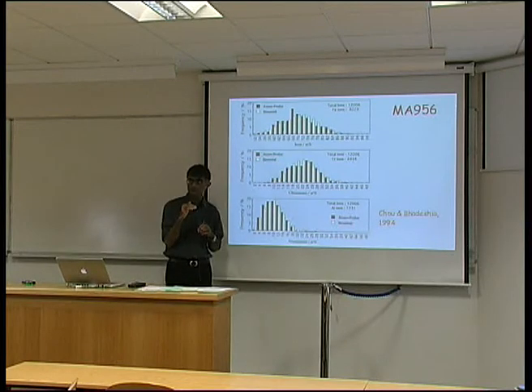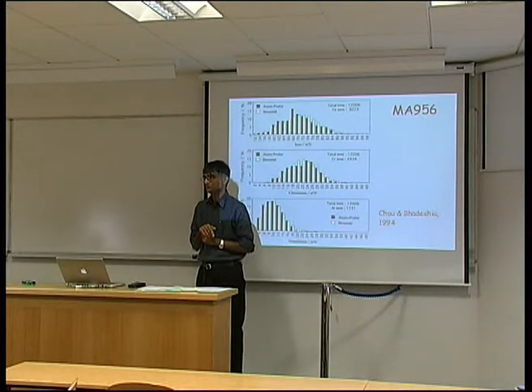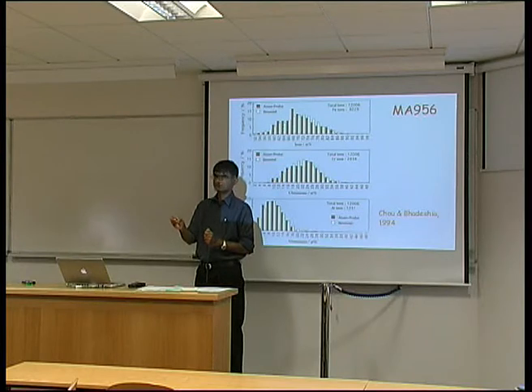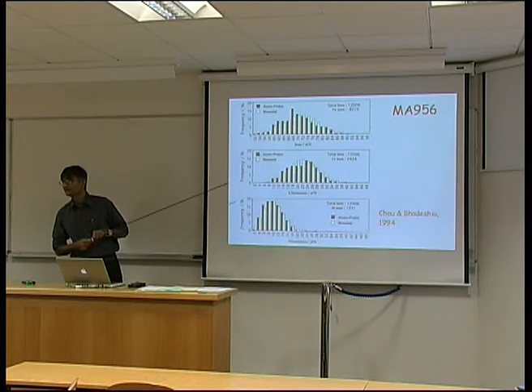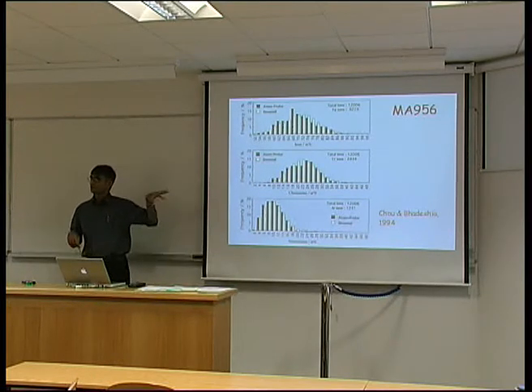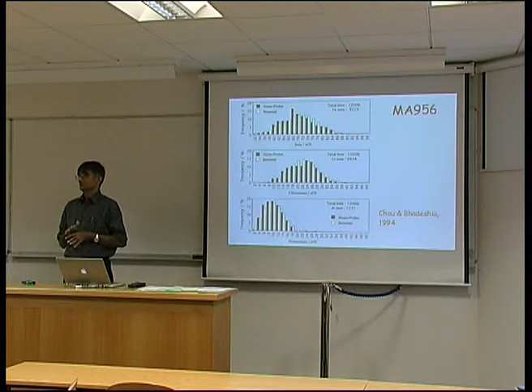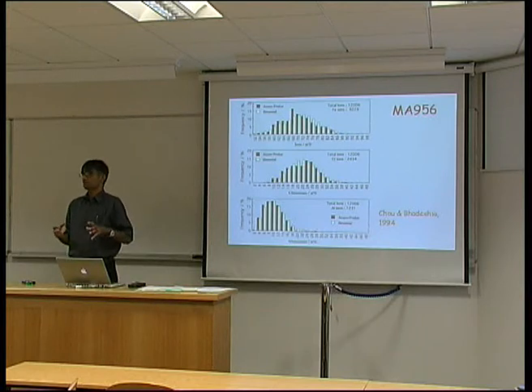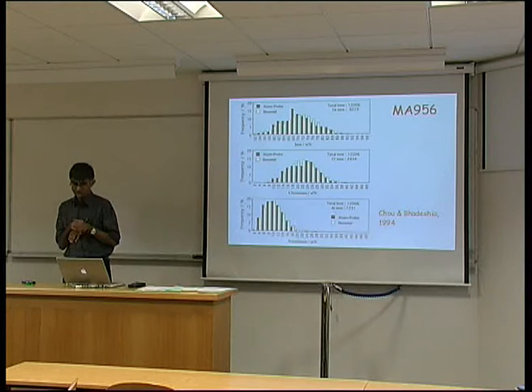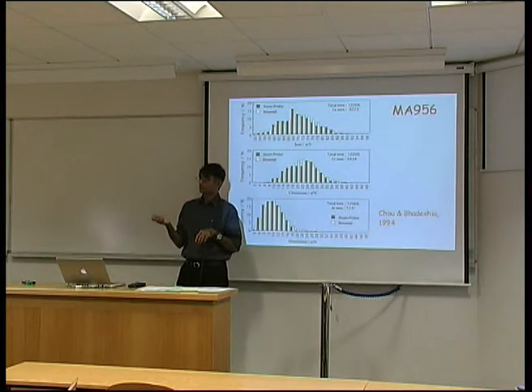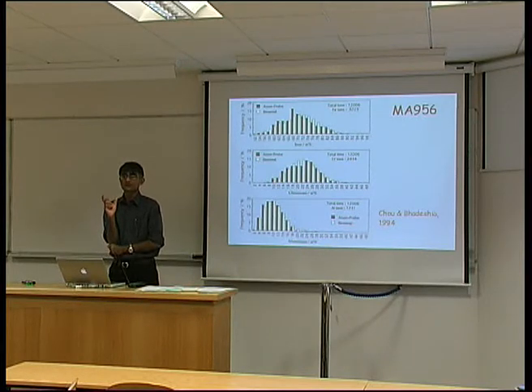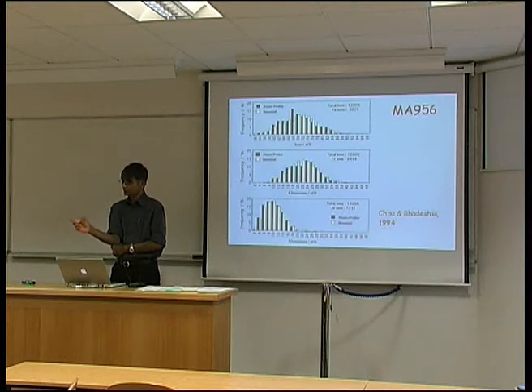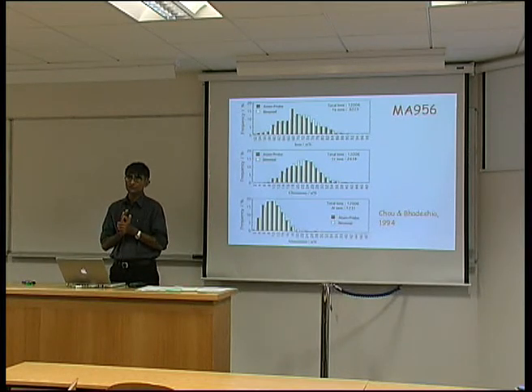From a thermodynamic point of view, the meaning of a homogeneous solution is that you have a random distribution of atoms. It doesn't mean that if I pick out 10 atoms I will get exactly the same composition as 50 atoms. When you look at distributions, you can do certain statistical tests and say within certain limits of confidence, yes, this is a random solution. It's very interesting because this is an iron-chromium-aluminium alloy and we've achieved a random solution, even though iron and chromium hate each other — meaning if you gave this material a chance, the iron atoms would cluster and the chromium atoms would cluster. We've forced them together by mechanical alloying — it's nowhere near equilibrium.